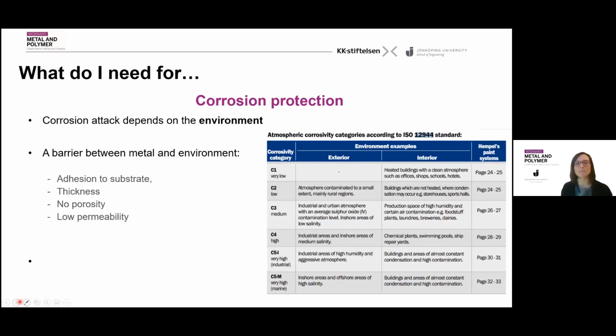Again, in order to exploit the potential of protection, you need 4 important parameters to be considered: adhesion to the substrate; thickness and its distribution over the whole profile of the surface; quality of the coating, so no porosity should be there, the coating should be continuous in order to be a barrier; and low permeability to aggressive elements in the atmosphere, humidity and pollution being the main factors.